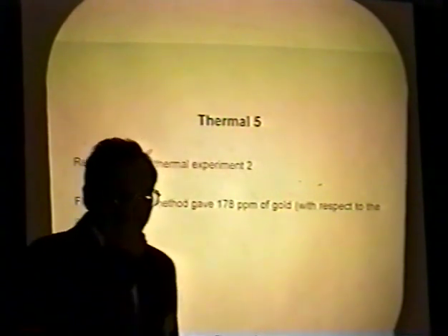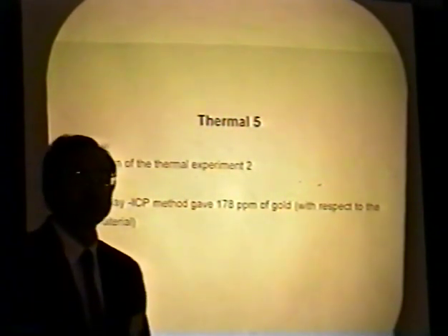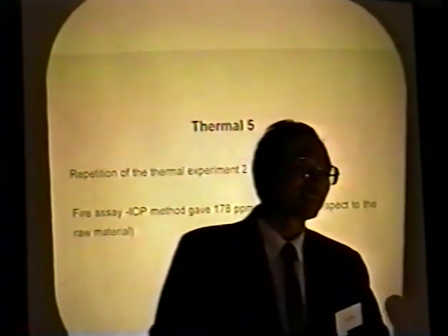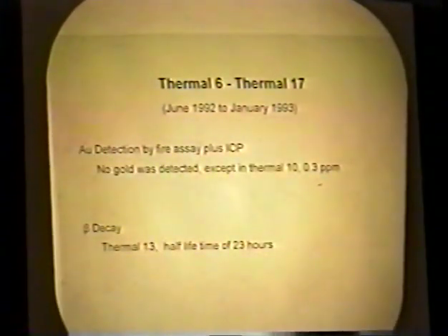Now that's the basic experiment we did in the first 5 runs. Looks pretty nice. Unfortunately, later we really didn't get good results. For some reason I don't know, but anyway we didn't get good results. Later, Thermal 6 to Thermal 17, from June 1992 to January 1993, we detected gold by fire assay plus ICP, and only in Thermal 10 did we get like 0.3 ppm. It's very little, and the other runs we didn't get anything. For the beta decay, we ran Thermal 13 and found the half-life time is 23 hours.